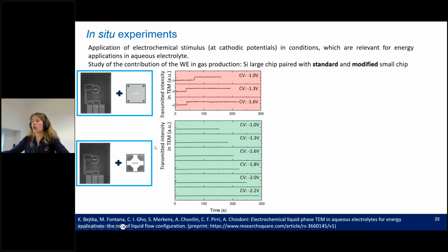So here I will show you what is happening and what is the contribution of the working electrode in gas production when we pair the large silicon chip with the standard and modified small chip. I show you the transmitted intensity curves acquired during the cyclic voltammetry experiments. And here you can see, and I showed you this before, that when we have this abrupt change in transmitted intensity, it means that the electrolyte layer is thinner because there is some gas produced there.